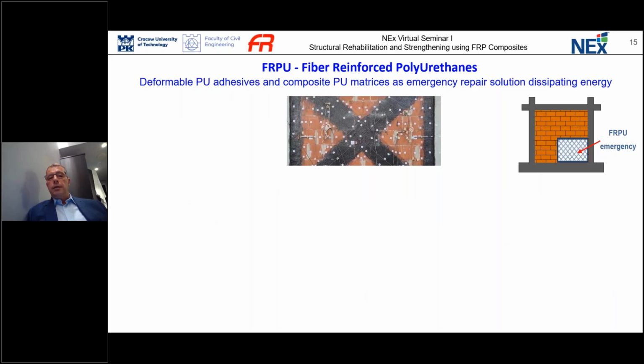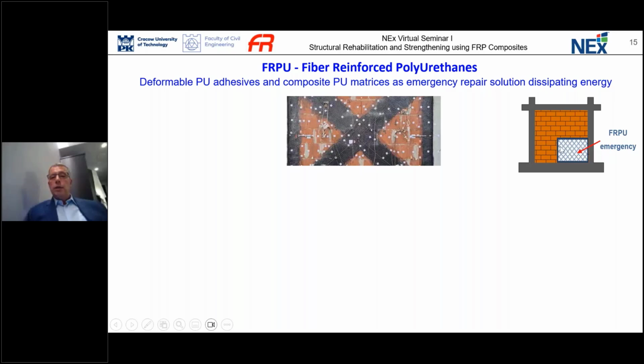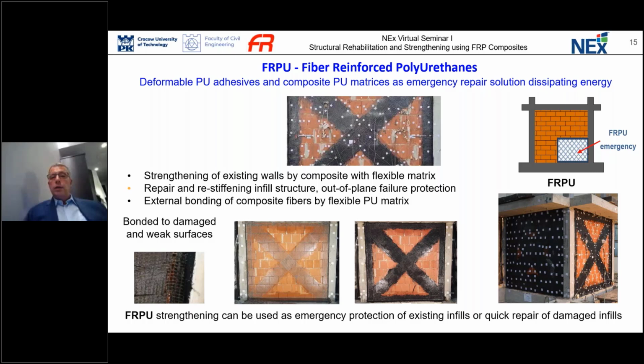I also present the ability of this kind of matrix to deform and transfer and dissipate energy when the load is dynamic or it is in fatigue. So we used it in strengthening of weak masonry infill when we had the reinforced concrete frame system. In this case, we used glass fibers in polyurethane matrix that were bonded to reinforced concrete columns and slab, and also to the masonry. So these both systems were constructed on the 3D real scale building that was put on the shaking table, and we were able to protect this structure against out of plane and also in plane failure.